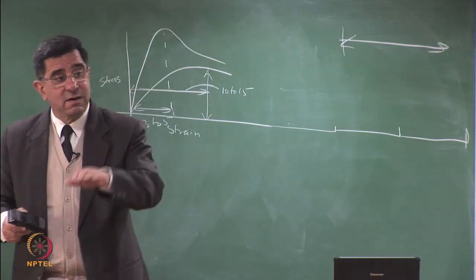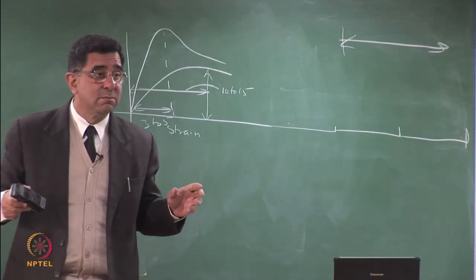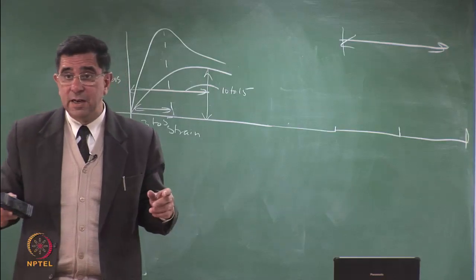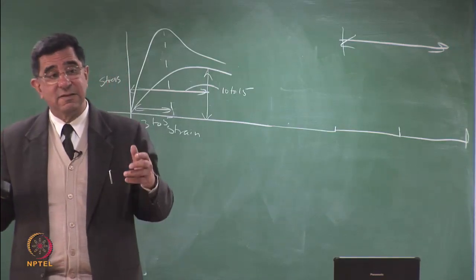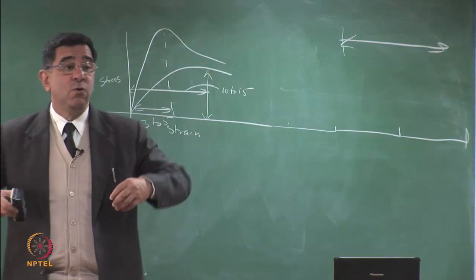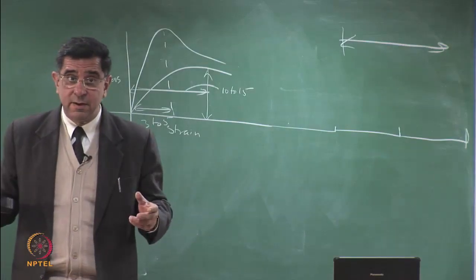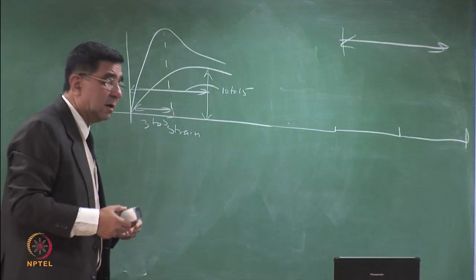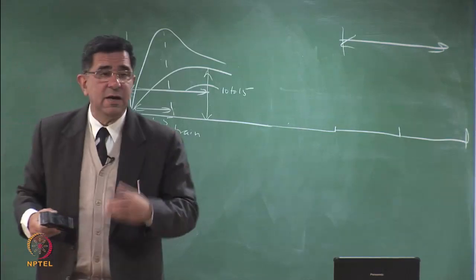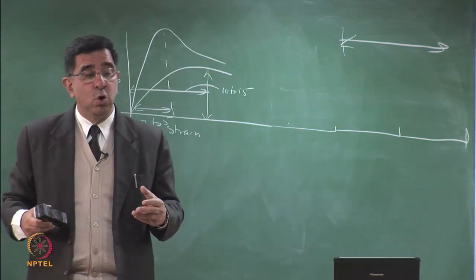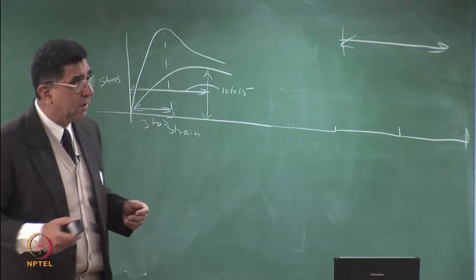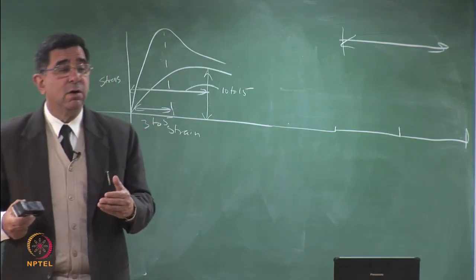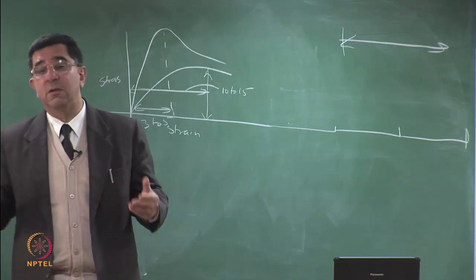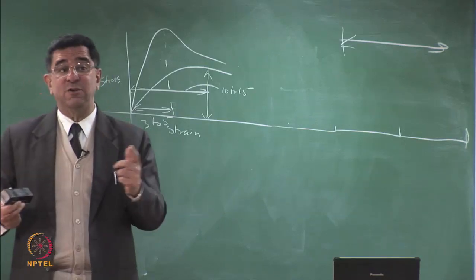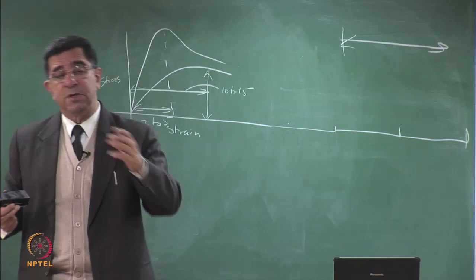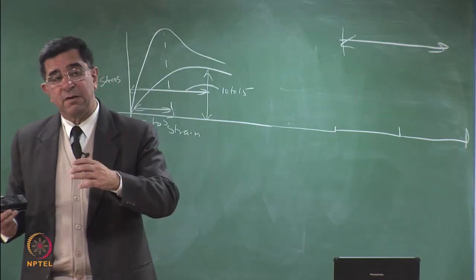Even if the base settles a little bit, it's not going to rupture or fail in tension. It's going to have that flexibility. And if you want even more flexibility, then there are other materials like VLDPE, LLDPE, low density polyethylene, which instead of failing at 50 to 100% would fail at 200 to 300%. But they will not be that strong. So it is going to be a tradeoff between flexibility and strength.